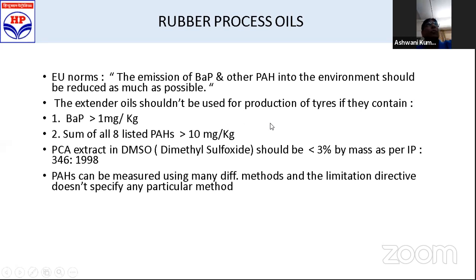They announced that we need low PAH, low polyaromatic hydrocarbons, so that the sum of 8 PAHs, which are already defined by them, has to be less than 10 ppm or 10 mg per kg. And benzopyrene has to be less than 1 ppm or less than 1 mg per kg. So on that basis we have developed a few low PAH grades, and they're widely used. MRF is using, Apollo Tyres is using. Many such customers use them, with PCA content, which we measure by IP346, less than 3%. As per DMSO extract, this can be studied separately.